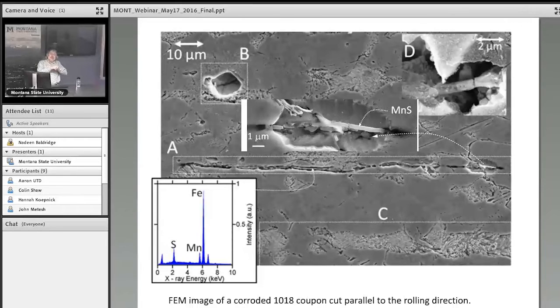So when the corrosion preferentially removes the iron around that, because that's where the most strain is, suddenly it is free of the iron that was hugging it, and then it snaps. In fact, it snaps so hard that this alignment is broken right here. So this is another thing. It's a release of stress you can see as a result of removing the material. So you can see all kinds of information. These are spin-offs.